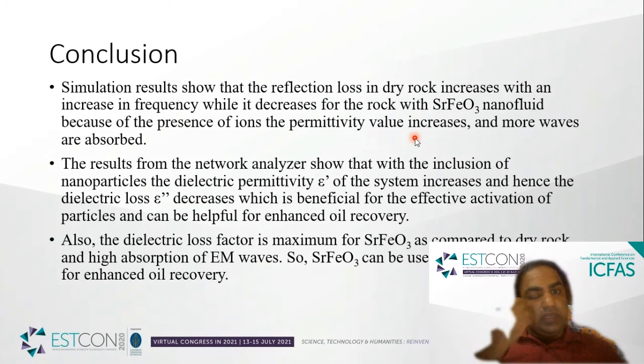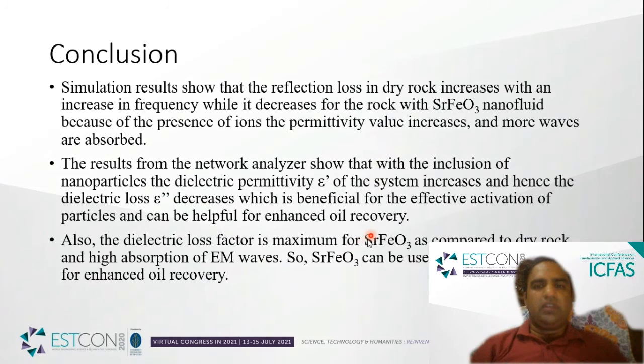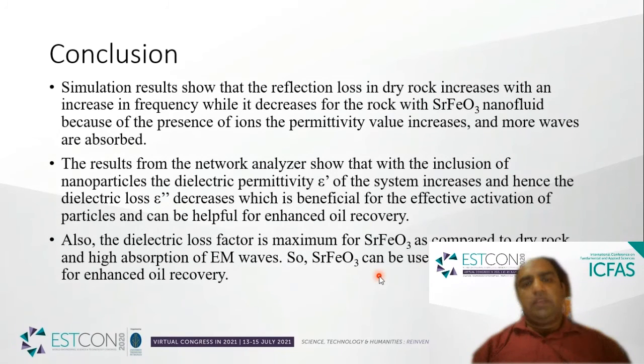The results from the network analyzer show that with the inclusion of the particles, the dielectric permittivity of the system increases, and hence the dielectric loss decreases, which is beneficial for the effective activation of the particles and can be useful for enhanced oil recovery. Also, the dielectric loss factor is maximum for strontium ferrite as compared to dry rock, and there is high absorption of electromagnetic waves. The strontium ferrite can be used as a potential material for enhanced oil recovery.